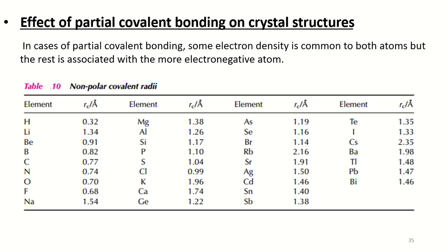Non-polar covalent radii can be measured accurately and represent a point of reference with which to compare other radii. Thus, the atomic non-polar covalent radius of carbon, given by half of the carbon-carbon single bond length, is constant at 0.77 angstrom in materials as diverse as diamond and gaseous hydrocarbons.